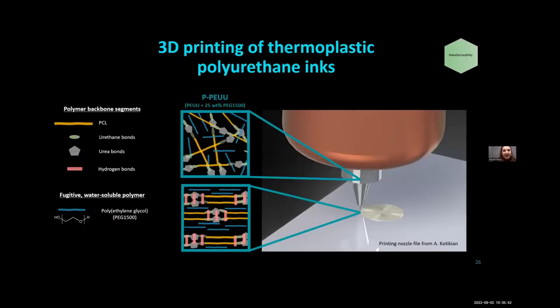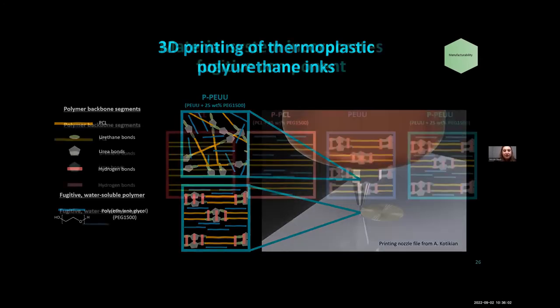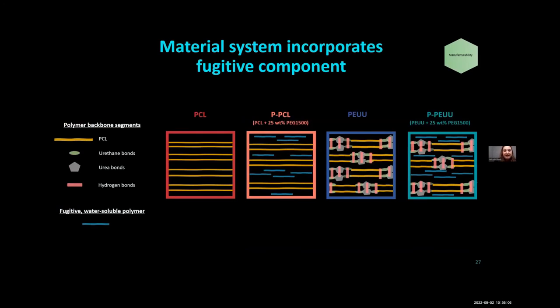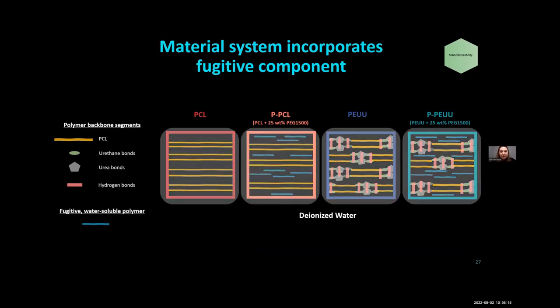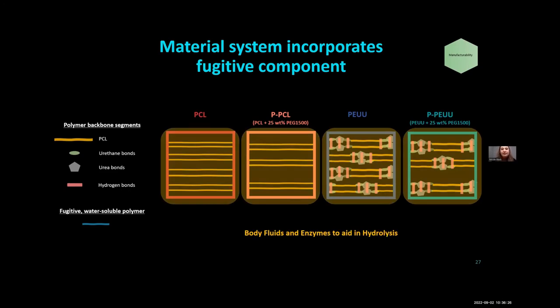So we essentially have this ink system whereby we have this biodegradable polyurethane polymer, and then we also mix in a water-soluble component and extrude via this melt extrusion process. So essentially you have this molten polymer in the syringe, apply pressure, and the material begins to be extruded. So we compared a bunch of ink classes. The PEUU is that polyurethane, and the PCL is an off-the-shelf polycaprolactone, with and without this water-soluble component, with the idea that this water-soluble component could aid in degradation. So after the fact, this component could be removed, and then more body fluids and enzymes could go into the graft to aid in hydrolysis.